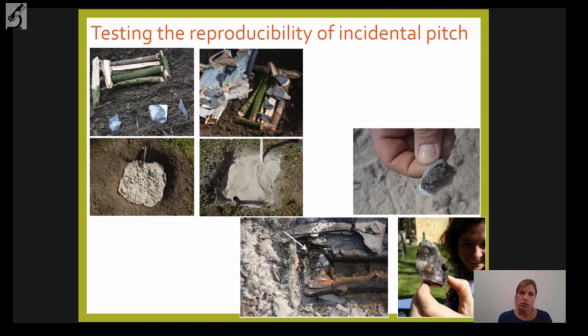For that, we again used a fireplace in which wood was positioned, and underneath and on top of that wood, we placed stone tools in order to examine whether such incidental pitch formed. Again, this experiment proved successful, and incidental pitch was deposited on the stone tools. This implies that the presence of pitch should not immediately be considered as evidence of hafting, as other causes may explain this presence.